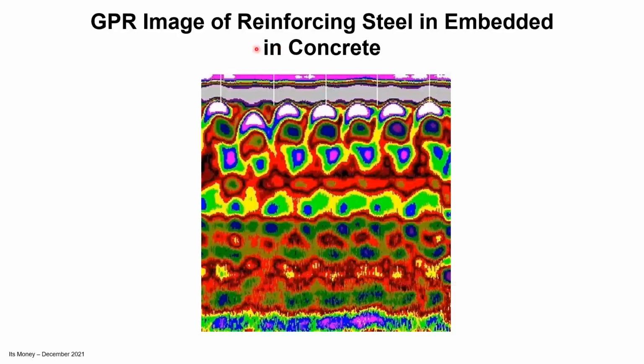And you can see here a very strong reflection from reinforcing steel, which creates a series of echoes and basically masks anything underneath. So you won't get any information about the underlying material in a heavily reinforced slab, grade beam or cap. Assessment of sheet piles.